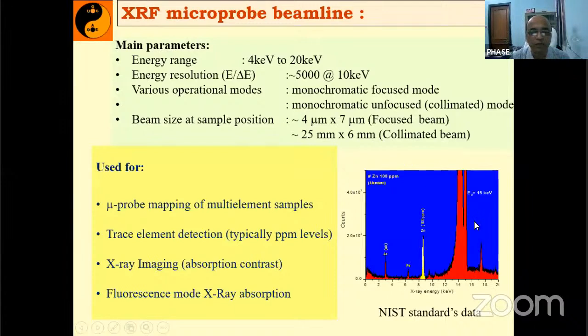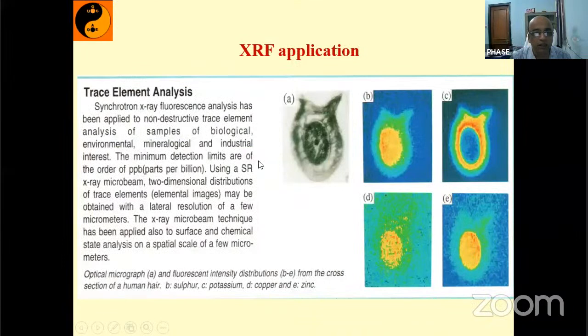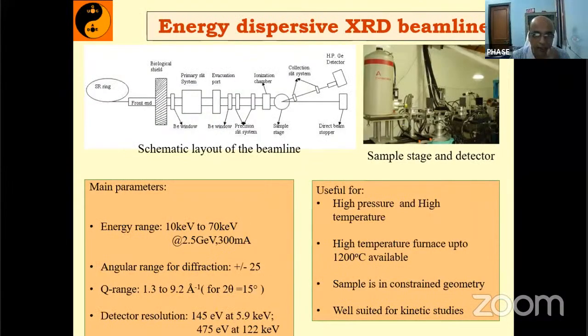Normally people use SEM and EDAX in the laboratory, but EDAX has limitations, and you can have only ppm level resolution. However, one can go higher with the synchrotron radiation beam. One can have the X-ray fluorescence, and that beamline is also available, to get the composition details. So this is the trace element analysis of a hair sample. A human hair cross-section was taken and we found out what elements are present in it. This is an X-ray fluorescence application, and a lot of people may be interested in this.